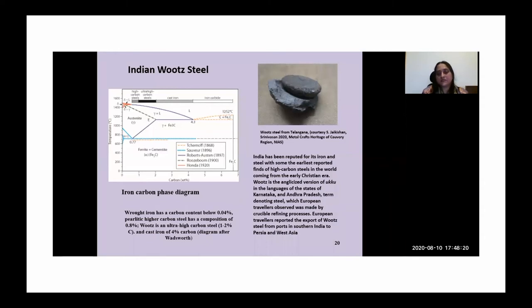But the Chinese mastered the technology of cast iron very early on, and already by the early Christian era, cast iron was being used extensively in China in the Han period and so on. And the other region in Asia which seemed to have developed an early mastery of using higher carbon alloys was the Indian subcontinent, where the use of wootz is known to have been prevalent. And as I said, it's described as an ultra high carbon steel with between 1 to 2% carbon. And you're looking in the above picture at a typical ingot of the wootz steel. This is from the Telangana region, through our collaborator in the region, Dr. Jai Kishan. And you can see it also with a fragment of a crucible.